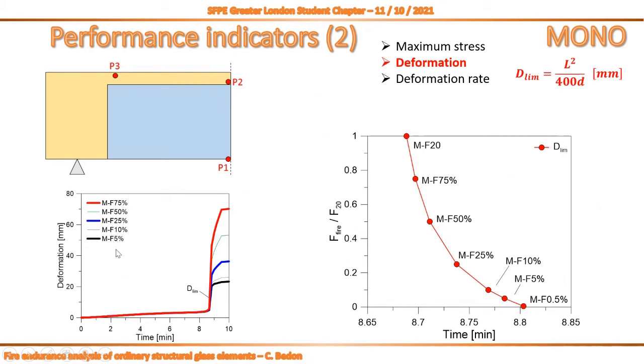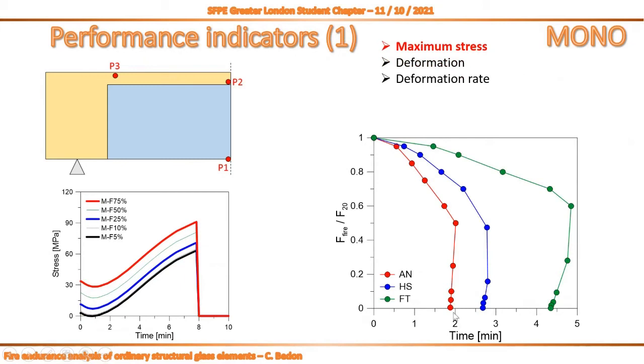What happens when we try to check this failure limit against different magnitudes of vertical load in fire? It happens more or less that the failure condition is, let's say, simultaneous for all of them. So this means that the mechanical load has a very small effect compared to fire if we want to apply a conventional deformation limit to our beams. Just imagine that we are talking about 8.7 or 8.8 minutes of exposure capacity, which is very big compared to the stress check, where our reference was in the order of 2 to 5 minutes of exposure.